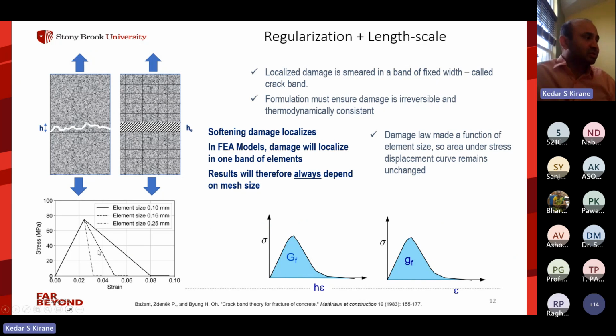So this is one illustration here. What it shows is the stress versus strain, shown on the right schematically; its slope will change with changing element size. So the larger element size will have a steeper slope. Now, of course, the simplest strategy is to calibrate the model with one element size and then not change that size for all the simulations. Then you can be sure that this problem itself doesn't occur. And that is what we did.